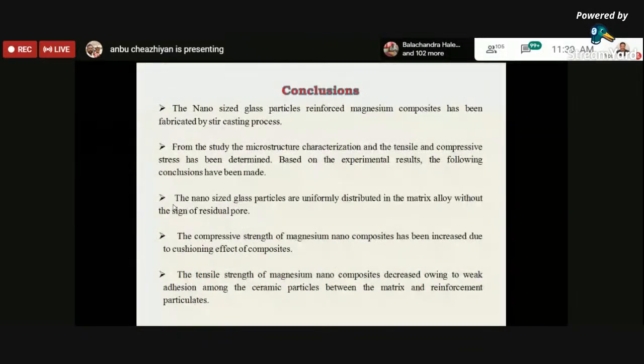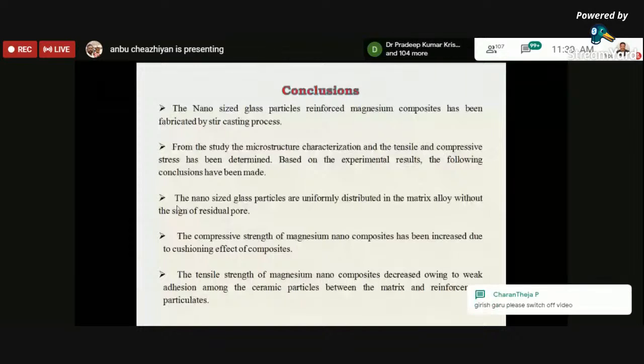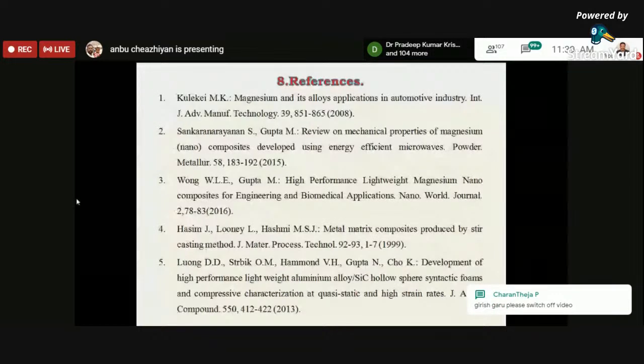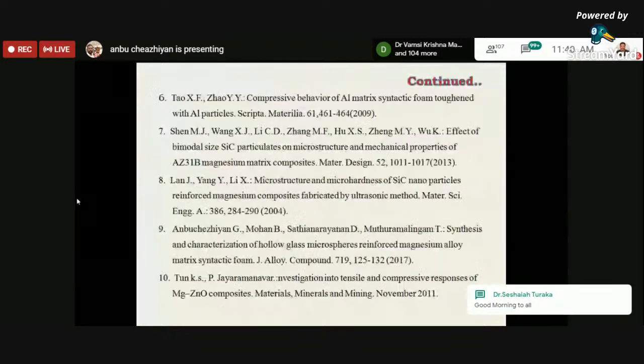So here, the nano-sized glass particle reinforced magnesium composites have been fabricated by the stir casting process, followed by microstructural characterization, and tensile and compressive testing. It has been observed that the tensile strength is very much reduced, and the compressive strength has been increased. The decrease in tensile strength is due to weak adhesion between the ceramic particles, the matrix and the reinforcement particles. These were the references that I have chosen for this STP. And thank you all.